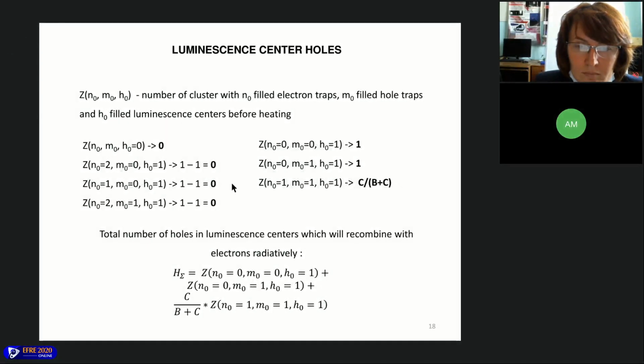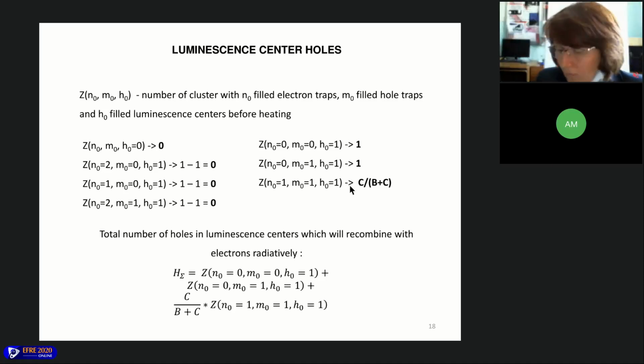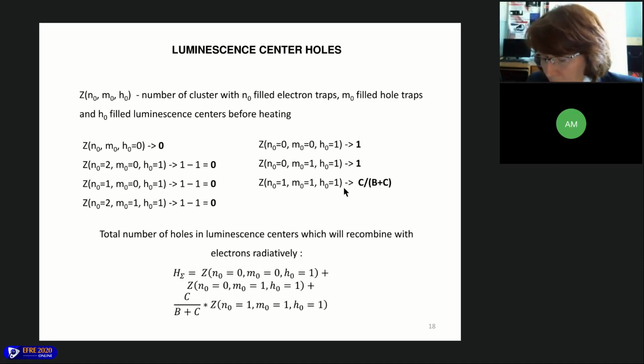Similarly, we will consider the expression for the number of occupied luminescence centers at the end of the low temperature region. The main difference in the localized competition between hole trapping centers in comparison with the previous case is represented in the case with a cluster which contains both luminescence centers and a deep trap occupied by a hole and one occupied electron trap. In that case, we can estimate the number of occupied luminescence centers after the low temperature region using values of the corresponding probabilities, coefficients B and C.